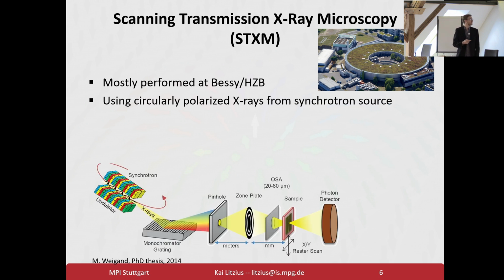To get more of an experimental idea of what's happening in the system, we do scanning transmission X-ray microscopy, STXM for short. That's a synchrotron-based technique. We're mostly performing that at the synchrotron BESSY II in Berlin. The general idea is that we have a synchrotron that generates X-rays. We don't need to care about that for the moment. We monochromatize them to one absorption edge so that we are sensitive to only one element at a time. That makes it easier to distinguish elements, and we can go deep into a sample, et cetera. Then we focus these X-rays with a zone plate, essentially an X-ray lens, onto a sample. The X-rays come out of the sample on the other side, and we just count them with a photon detector.